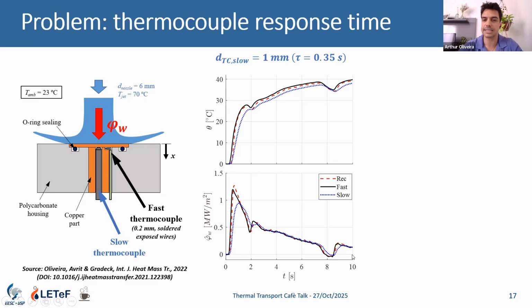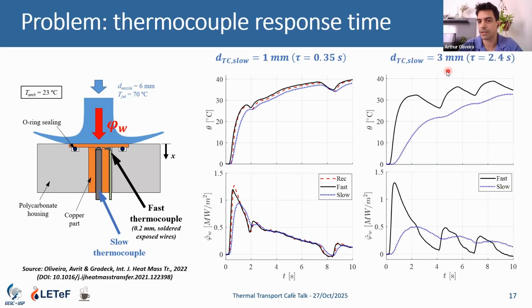We also tested that for a very slow thermocouple, a 3 millimeter thermocouple with very slow response time. You can see the response time is comparable to the experiment time.